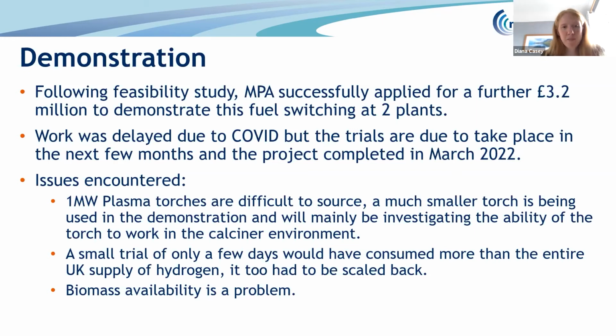Secondly, we found that a small trial of only a few days would have consumed more than the entire UK supply of hydrogen, which was a bit of a shock. Well, it was a shock to me anyway, because hydrogen's talked about a lot, and this was just a tiny trial for a few days at one cement plant. So just to find out that the hydrogen just wasn't really there was a bit of a surprise. So we had to scale that back too, but we should still get some very useful results from that part of the trial.